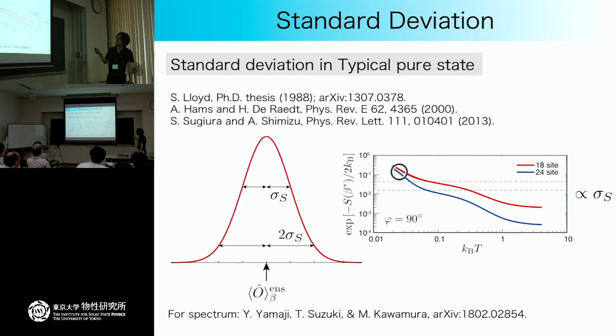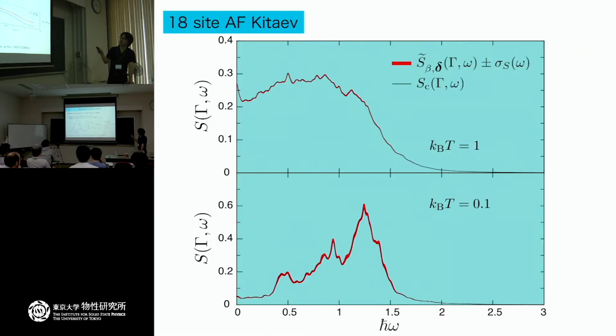If you enlarge the size of the spin clusters from the 18 site to the 24 site, then this quantity becomes smaller and smaller. For high temperature it's really small, and at low temperature it becomes larger. And this gives you the standard deviation. So if your system size is large enough, then this standard deviation becomes really small. This is discussed in these papers. And even for the finite temperature spectrum, this situation is also true.